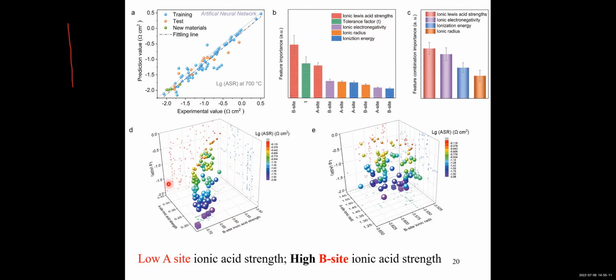To achieve the lowest area specific resistance, we need a low A site ionic acid strength and high B site ionic acid strength. However, when we look at the ionic radius, we didn't find a very strong correlation between the radius and the area specific resistance. So we believe the ionic acid strength should be a very important descriptor to help us screen materials.